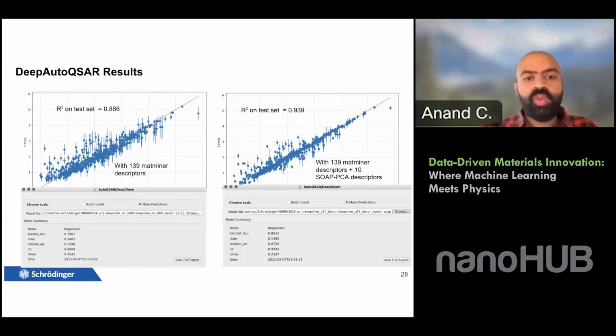These two models here show that we are able to get a pretty accurate model to predict the band gap of this class of systems using 139 MatMiner descriptors. The R square is around 0.88. And with 139 MatMiner descriptors plus the SOAP PCA descriptors, we're able to improve the R square from 0.88 to around 0.94. So by really combining the appropriate descriptors for the appropriate chemical space, we're able to improve the performance of the machine learning model.